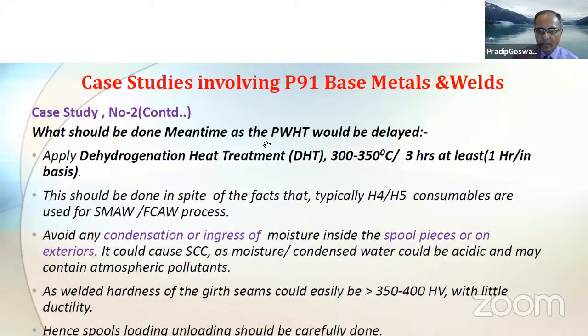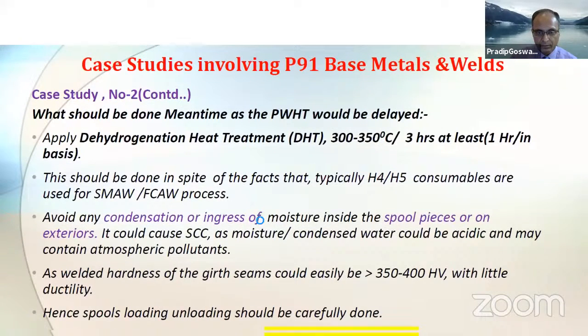What should be done in the meantime, as the post-weld heat treatment would be delayed? Answers: a few possible solutions. Apply DHT, dehydrogenation heat treatment, typically at 300 to 350 degrees centigrade for at least about 3 hours, typically on a 1 hour per inch basis. This should be done in spite of the fact that typically H4 and H5 consumables are used for stick as well as flux core arc welding processes.